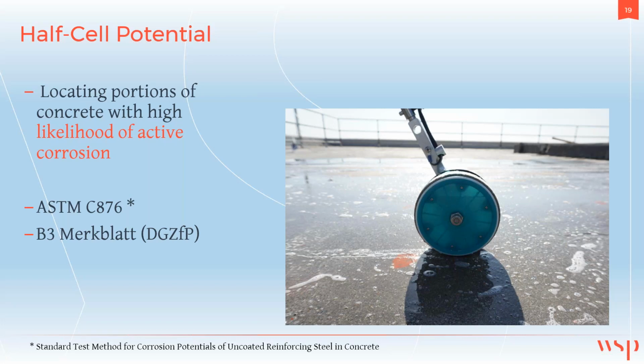However, in certain situations, it's better to have a corrosion technologist or expert involved because it's not always straightforward interpretation based on the absolute value that comes out of the test. There are a number of things that affect the response, including temperature, the moisture condition of the concrete. Another thing to keep in mind is that the probability that comes from this is not an indication of corrosion rate.